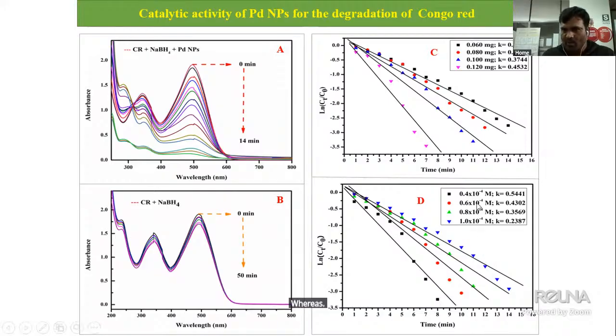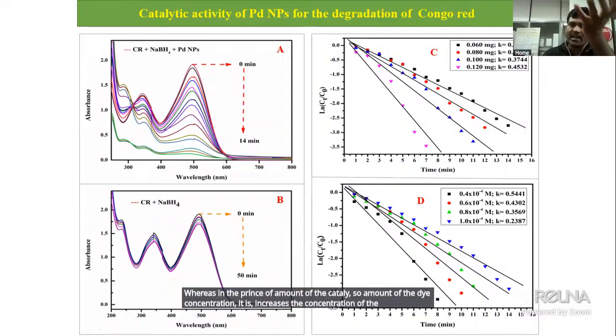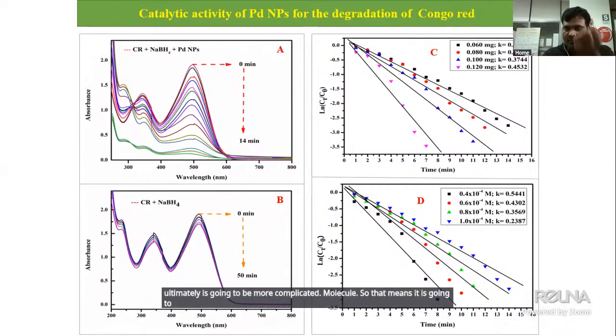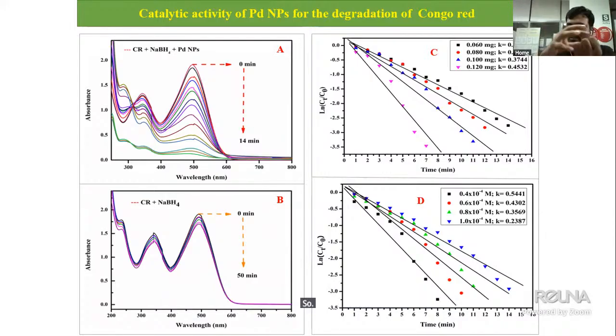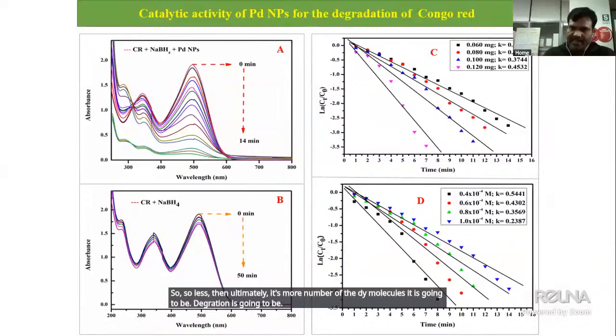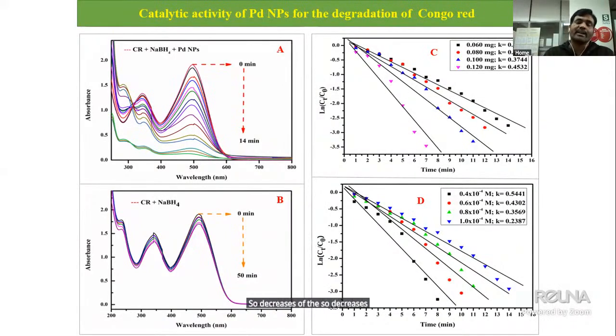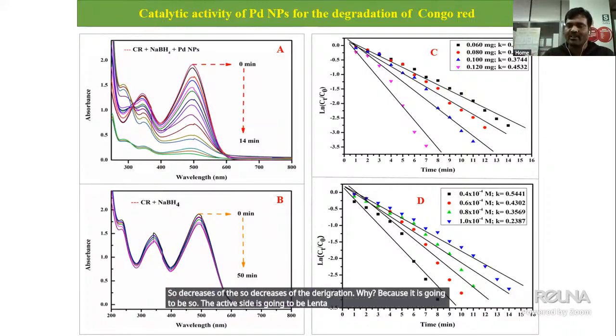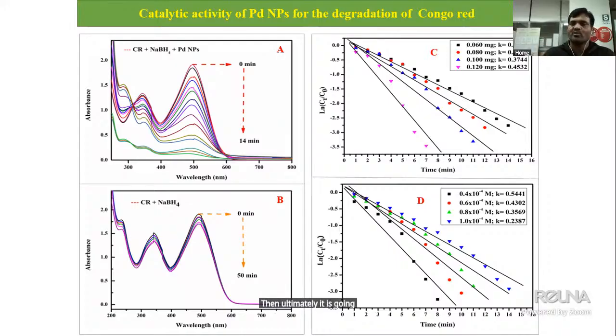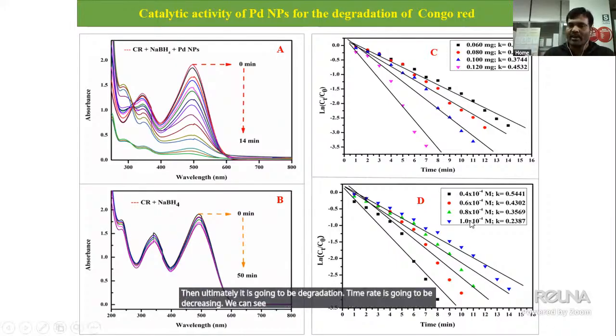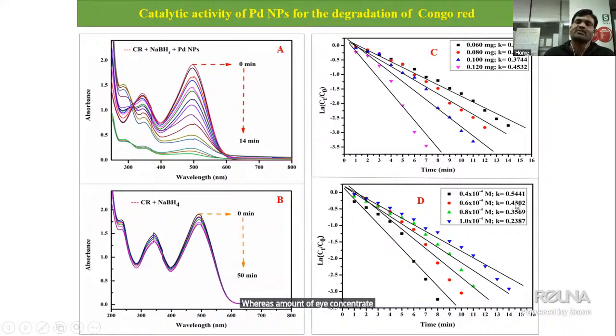Whereas, at a fixed amount of catalyst, as the dye concentration increases, there is more competition among the dye molecules. The sufficient active sites become less, so more dye molecules compete for degradation. The dye degradation decreases because the active sites are limited in number. Then ultimately the degradation rate decreases. We can see here that as the amount of dye increases, the rate constant decreased.